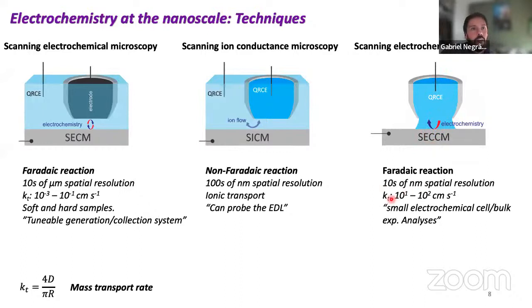Because it's a small tip, it has a very high mass transport rate. So you can see that's better than the SECM for this, just for the size, because of tens of nanometers of size. It means I can investigate much faster reactions. So if you remember from my talk, we were talking about the kf, for instance, the forward rate constant of the chemical step, I could investigate those more here, or even the electrochemical step, the k0, I can investigate those at the top edge, where the limit will be much higher for this case.